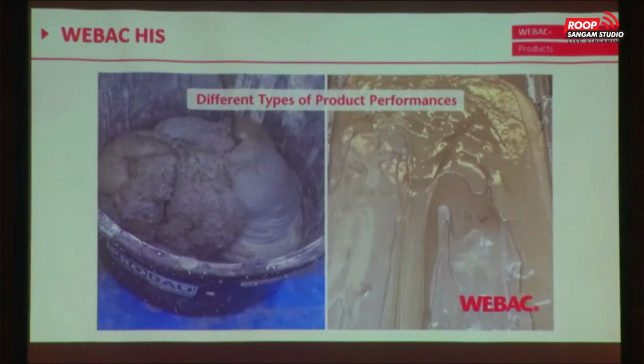On the left side, we did a test on a job site where we added 1 part of cement and 2 parts of resin to see if we get a foaming. That worked. And on the right side, it's not a video, but this shows the thixotropic effect, which will be added to the cement stream, which gives you the ability to block, to stop, to set a block with your cement and then shut off the PU pump and go back to your standard cement injection. It's not necessary to use the product permanently. Only in cases where you have some issues, then you can apply that product.